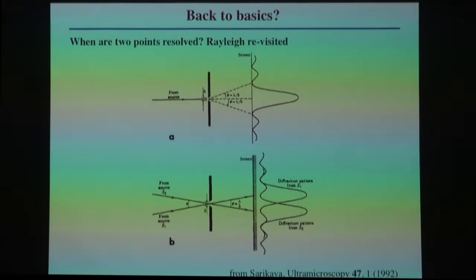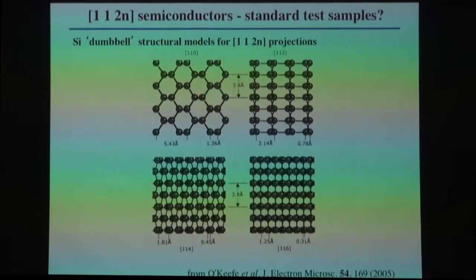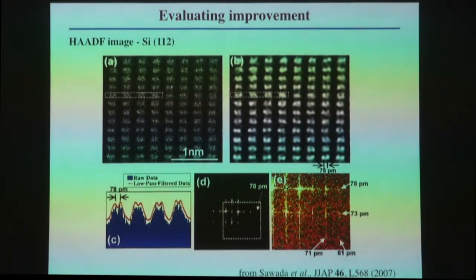Can we use a similar definition to determine the resolution of our particular microscope? If we're going to be suspicious about Young's fringes, and maybe we don't have the capability to get our phase plates, although these days you can get your phase plate quite easily on most of the aberration-corrected microscopes, O'Keefe said, why don't we look at the so-called 11N semiconductors? So for example, in the case of silicon in 110, there's a dumbbell pair of atoms that are separated by 1.36 angstroms. And then if you tilt to 112, then you have a pair of atoms, at least in projection, separated by 0.78 angstroms. And then if you go to 114, you have two atoms that are separated by 0.45 angstroms, etc. 116, 0.31.